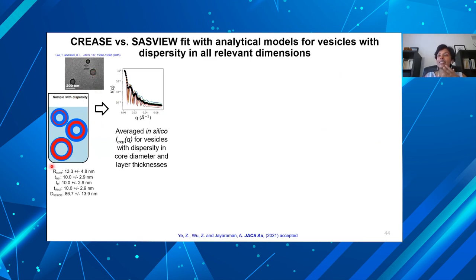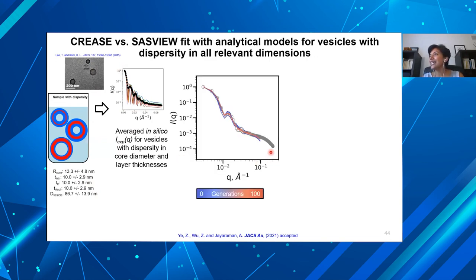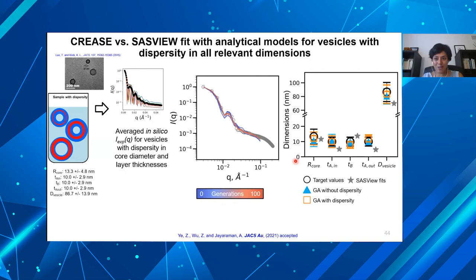So we basically said, let's take the hardest case of a solution with very dispersed vesicle diameters. And here we know the right answer, just like in the previous slide. Do we get these answers back? And do we do better than an analytical model fit? So clearly this is how noisy the structure factor, the scattering looks from this in silico experiment. This is how things look as the genetic algorithm progresses from low generations to high, how it fits. And then from that, we get the dimensions at the end of it.